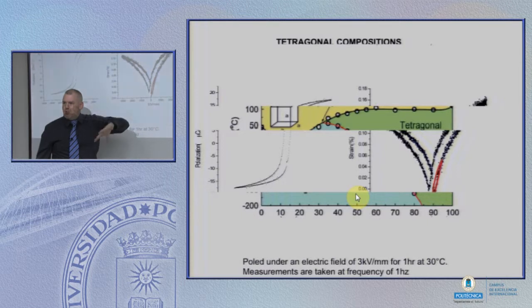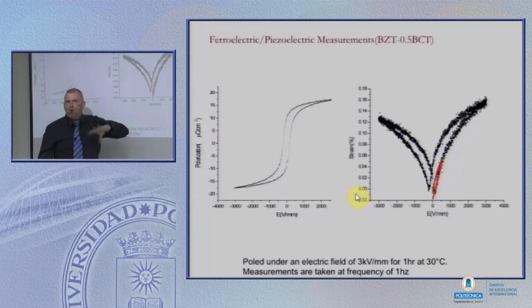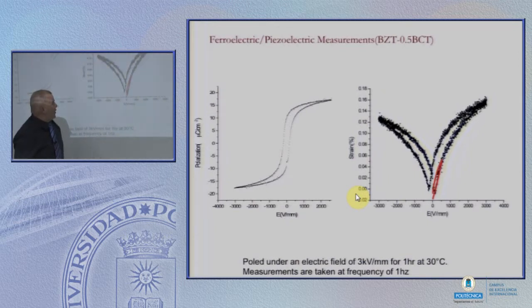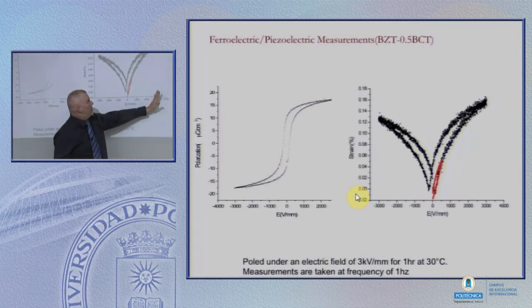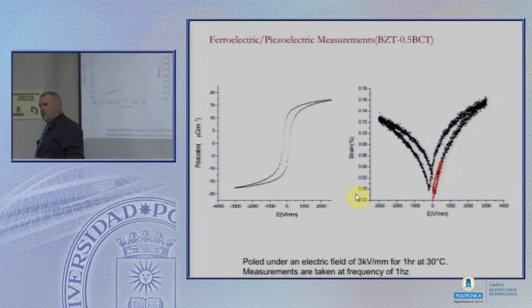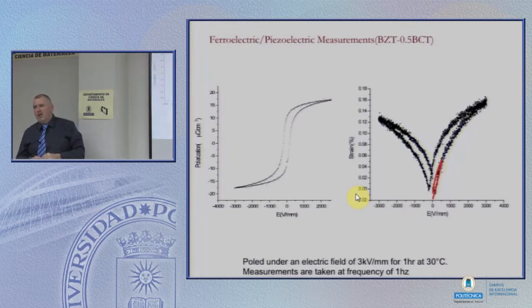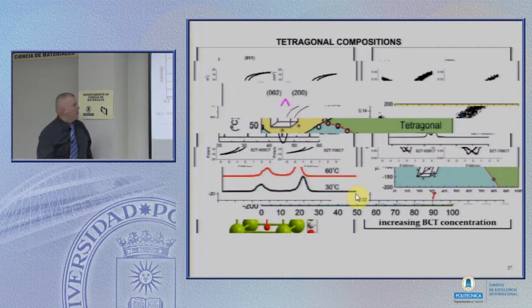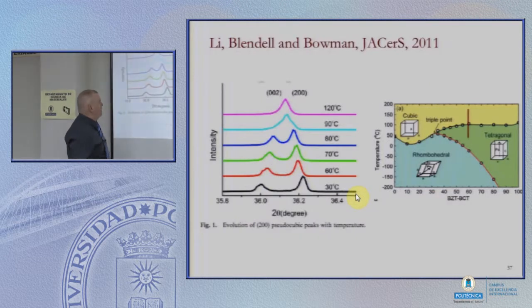If I go back to here, we had chosen our own poling conditions in terms of temperature and in terms of applied field, and the question of whether we use the same as what were being used in Tsukuba was on our minds. We applied as much field to these materials as we possibly could. It turns out, in this case, 3,000 volts per millimeter is a really large field. If your sample breaks down at that point, it's pretty scary. It's very surprising in these materials because they're not 100% dense. There are some pores, but they're able to sustain that large a field without blowing up, which is a good thing. So we also did a set of experiments exploring temperature.